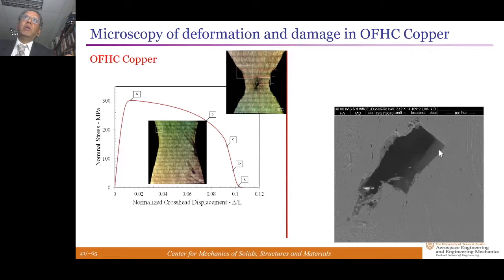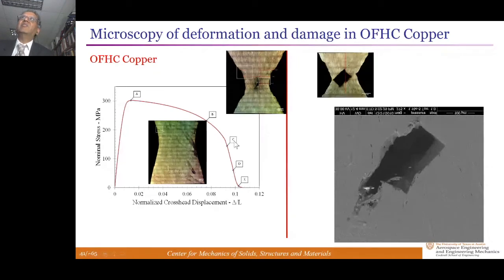If you continue loading to the point D, that rectangular cavity remains a rectangular cavity and enlarges inside. So there's some interesting mechanism that is underlying that. If you slice that perpendicular and go in the third dimension, it's a tunnel. So this rectangular cavity is a prismatic cavity that forms along the width direction of the specimen.